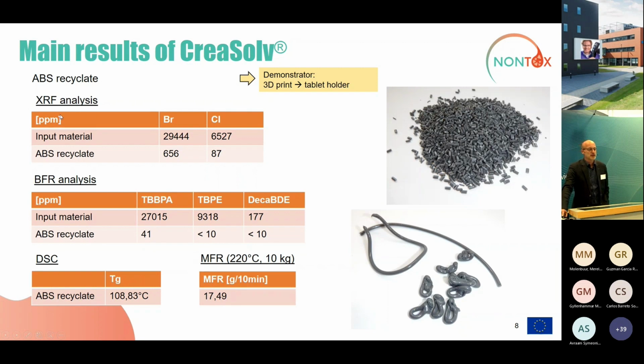First of all, the good news is here looking into the ABS recycled materials. The XRF analysis of bromine and chlorine in feedstocks and the recycled material clearly indicate we are able to reduce chlorine and bromine significantly. If we have a specific BFR analysis, bromine flame retardant analysis, we see that the majority, or the main flame retardants in such fractions, TBBPA, TBPE, and DecaBDE, are also highly significantly reduced.